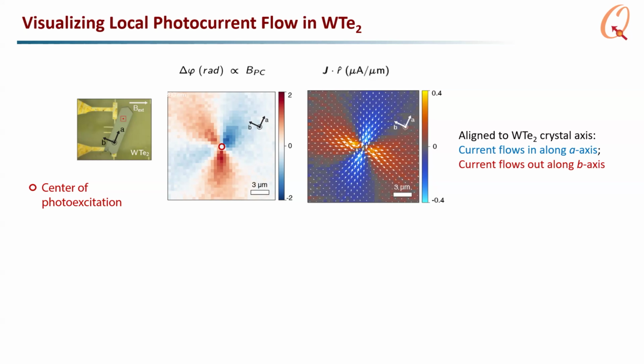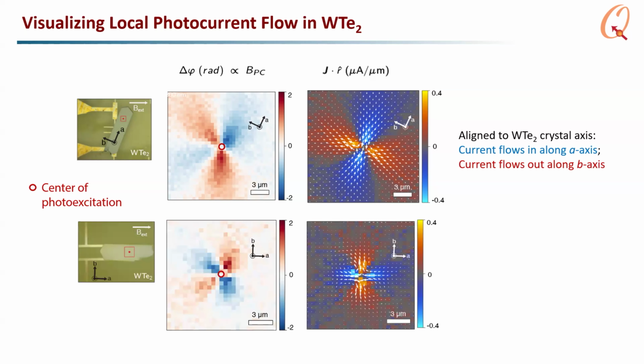So is that a fluke? Just for this one sample? Well, I can rotate the sample and map the photocurrent again, and then the pattern of the field I get rotates, and it again indicates that the local photocurrent is circulating in a manner that's aligned with the crystal axes.